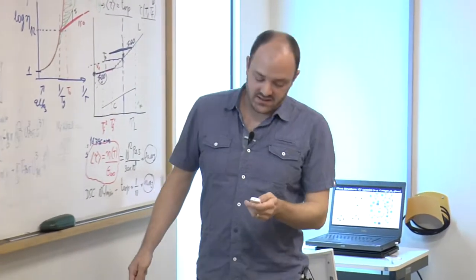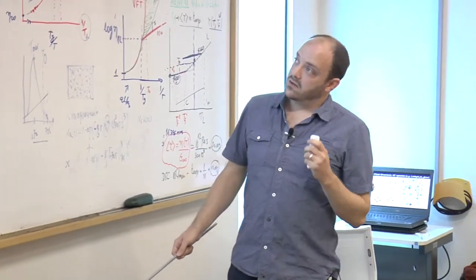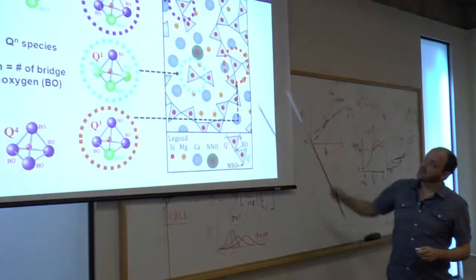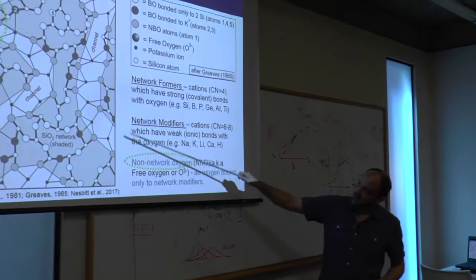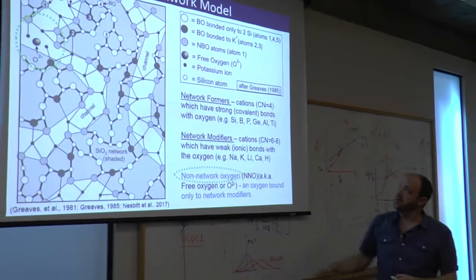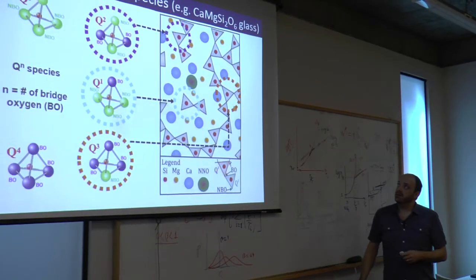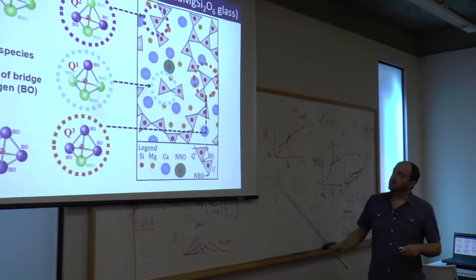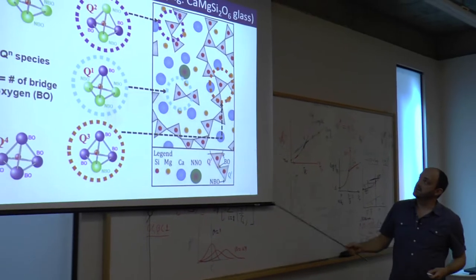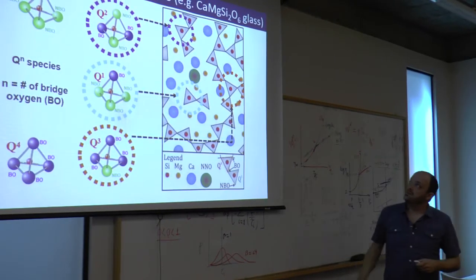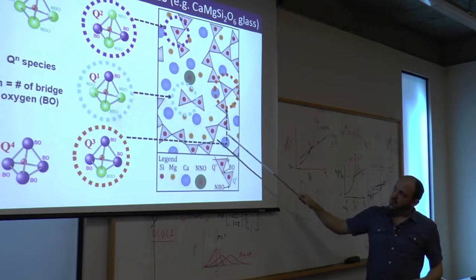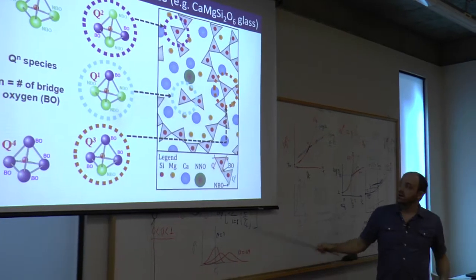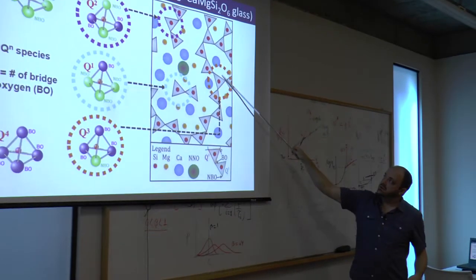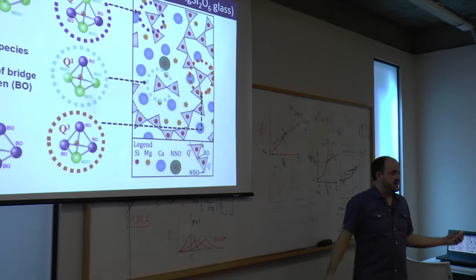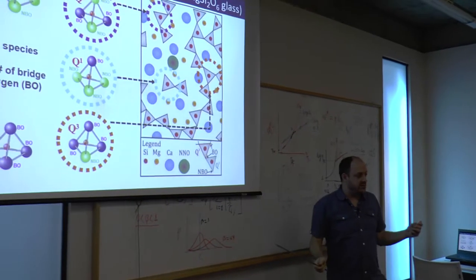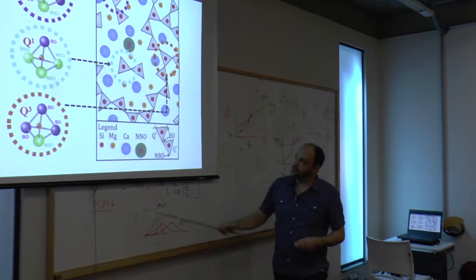One of the other features we can look at is this silicate part of the network. In this case we have sodium and potassium in the network. Here I've taken a 2D image of an imaginary diopside glass, this calcium magnesium metasilicate. And we actually get different vibrational frequencies from tetrahedra that are bound to different numbers of other tetrahedra. In the most general sense of the term, it's the same as that mass effect.